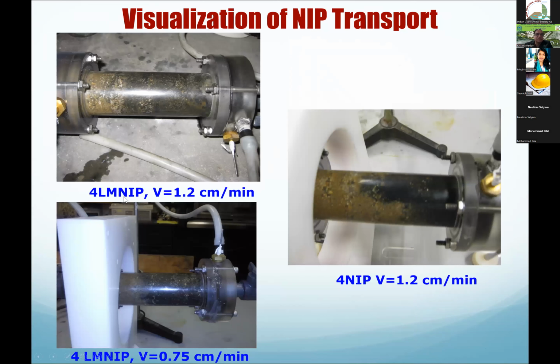This is 4 grams per liter lactate modified nanoiron particles with a flow velocity of 1.2 centimeters per minute. So we're injecting it. You see the color of this. That shows that it is transporting. The good part of this research was that these nanoiron particles are dark in color, so visualization becomes easy. So this is during the column experiment.